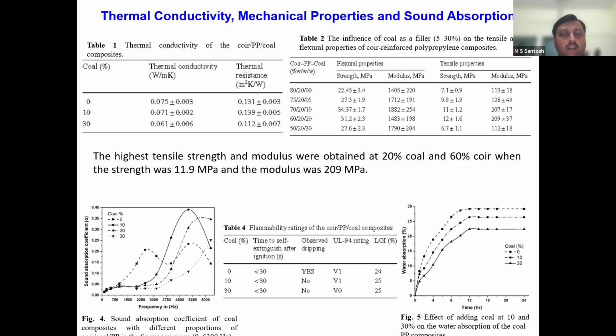So when you look at some of the other properties like sound absorption as well as water absorption efficiencies, there are clear indications that the 10% coal composition shows a much higher sound absorption coefficient, where it acts as a more soundproof material compared to its various other compositional percentages.